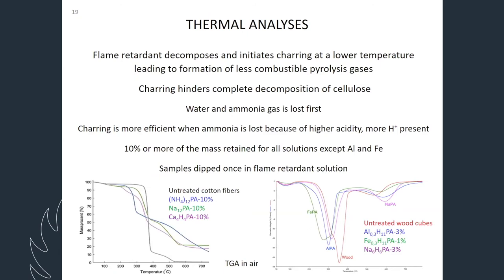Now we do the analytical methods. We start with thermogravimetric analysis. The flame retardants' action is that they decompose and start the charring process, as Anagarin described earlier, at lower temperature than untreated sample. And that actually leads to formation of less combustible pyrolysis gases. And it also hinders complete decomposition of cellulose, as you've seen in my videos, that the cotton did not disappear completely in case of treated samples.